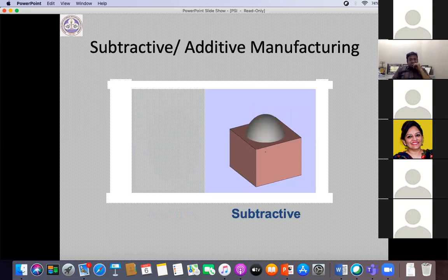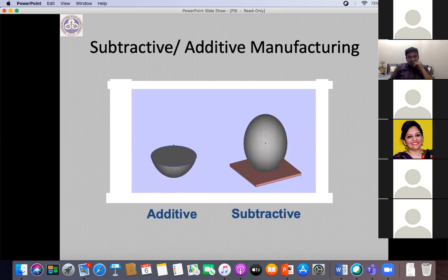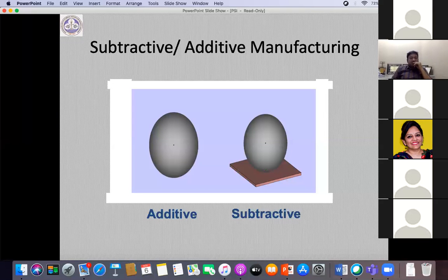Like this. This is subtractive manufacturing. A lot of waste happens in subtractive manufacturing, but the finished product is very fine, microscopically or macroscopically, just like your dental implants are. The surface of the implant is very important in the context of osseointegration. Hence, subtractive manufacturing is better for a dental implant.